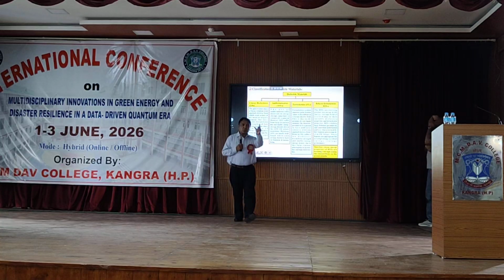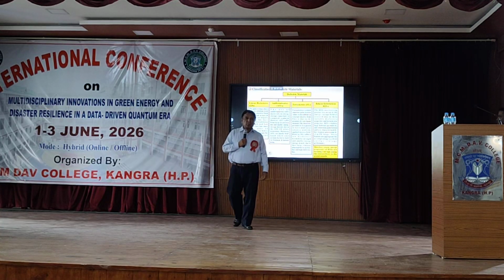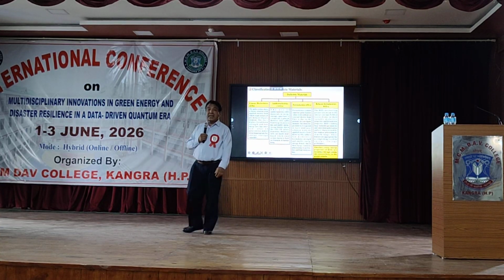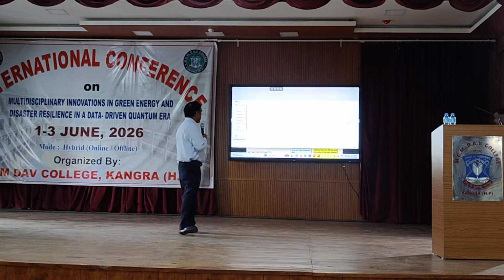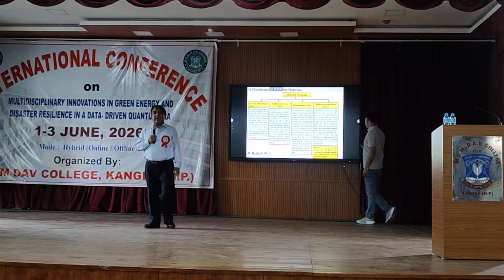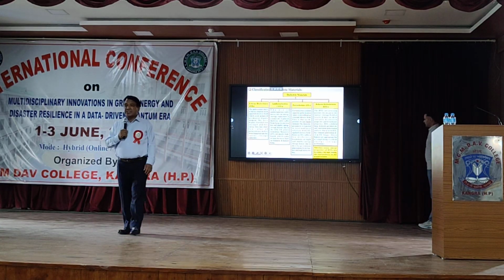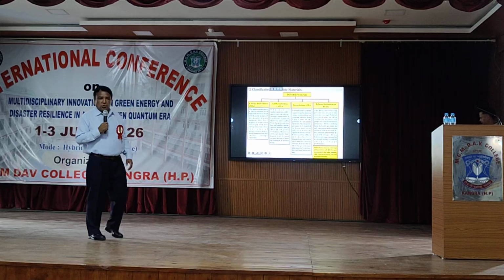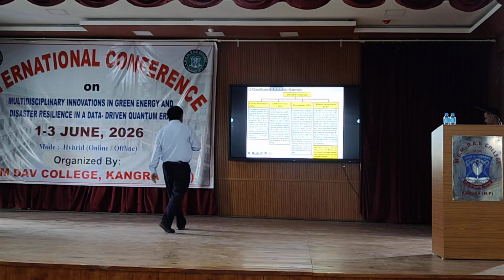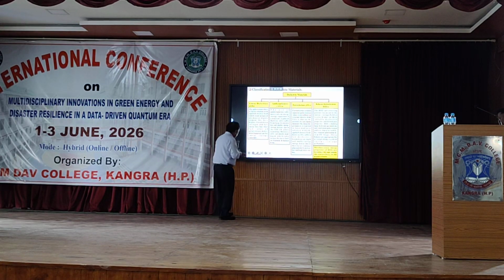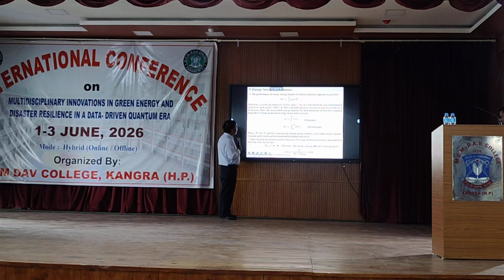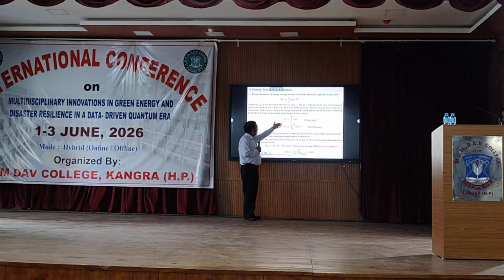Ferroelectric materials show very square hysteresis loops and are not useful for enhancing the energy storage density. The last one, relaxor ferroelectric, where we have polar nano regions, is promising to enhance the energy storage density. Because of the fact, if you try to see here how we evaluate energy storage density, this is for recoverable energy, total energy.